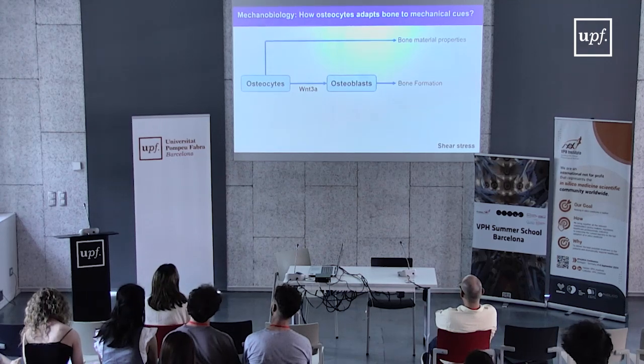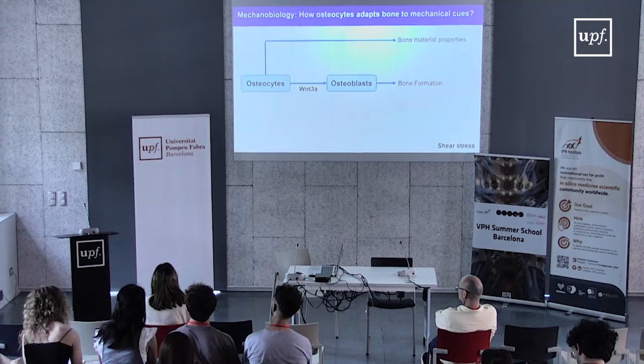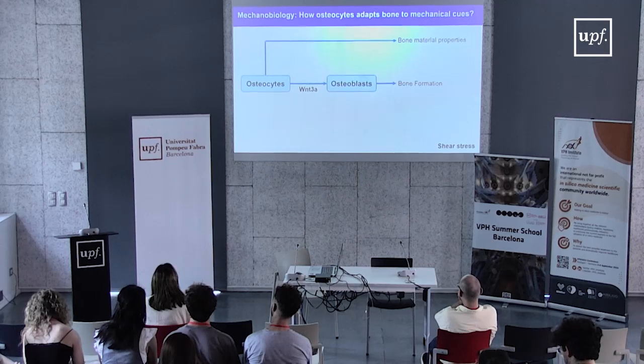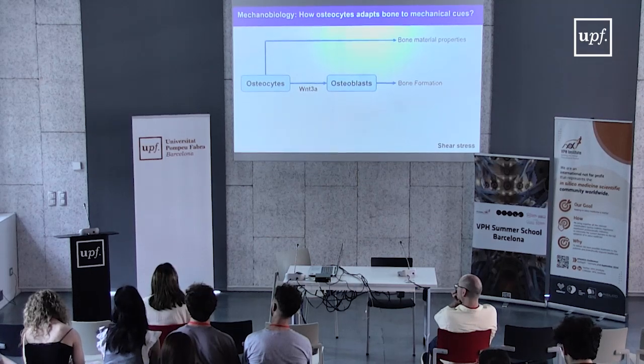Osteocytes can also induce bone remodeling by themselves all around their dendrites and lacunae, and adapt locally the bone material properties. And usually what they do is that they increase the degree of mineralization of the matrix, and they increase the amount of cross-linking of the collagen until they cannot sense these mechanical forces anymore.